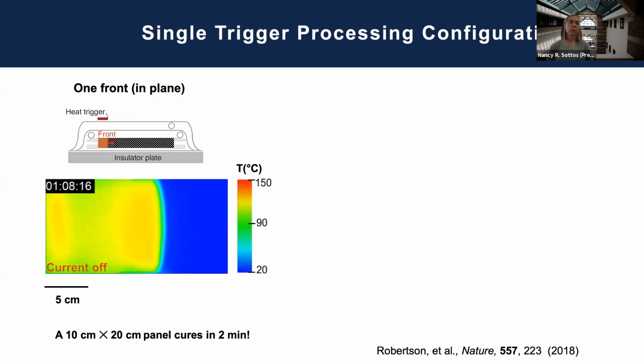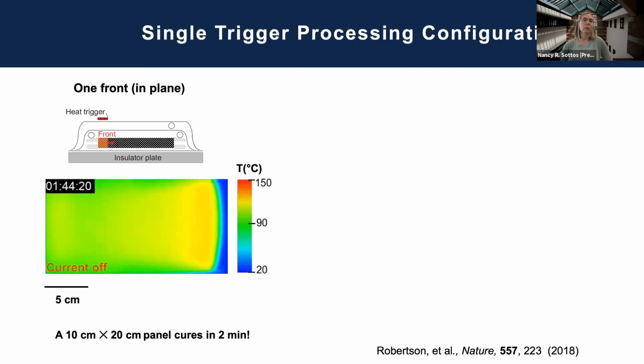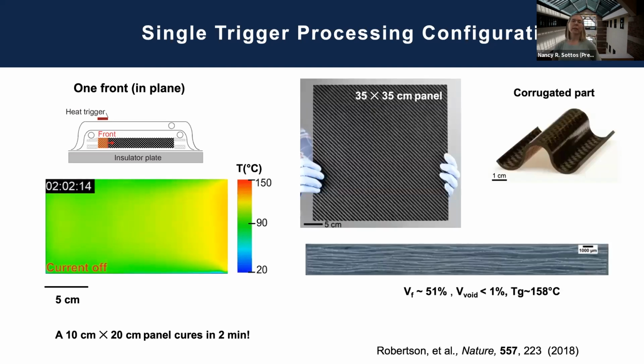And we are able to fully cure this panel, as it says on the bottom, a 10 by 20 centimeter panel in just 2 minutes. Again, on a desktop with very simple tooling. We've made larger panels, we can make more complex shapes, and the volume fraction for this woven material is about 51%, very low void content. We've actually moved to a system that has no solvent in the resin system. And the Tgs that we've gotten to are approaching 160 degrees C for the Tg of the composites.